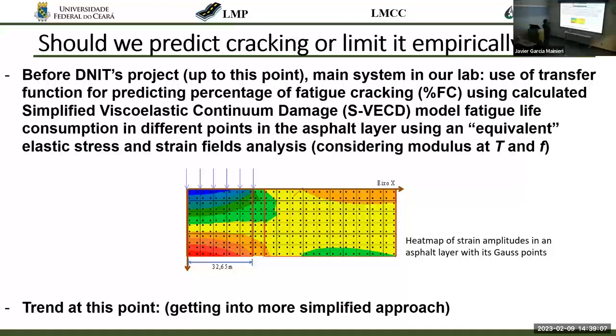We use S-VECD to calculate how many cycles we could apply at each point of the material, because in the pavement, let's imagine this is the asphalt layer, and below it, you have all the rest of the pavement. And we have different strain values at each point. So theoretically, you could have this point ending the service life, and this point that didn't even start to be used. So we need to take that into account. So our problem is very non-homogeneous.